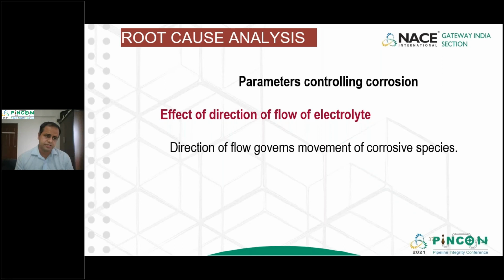Now, here I would like to present that suppose your pipeline is in a terrain where it is going from the top towards the bottom. Now, the flow of water will basically move along the pipeline through the path of the coatings. Now, it tries to penetrate the holidays and go deep inside. As long as your pipeline is along the terrain and water is going inside the coatings, it will try to ensure a good cathodic protection system. But the moment the seasonal variations occur, the outside electrolyte is no more available in the summer season, and water is already there inside the coating, which went inside during the rainy season. Because of that, the water content inside won't be able to be protected because the cathodic protection current has a barrier now. It is not able to establish a continuity between the outside and the inner atmosphere.